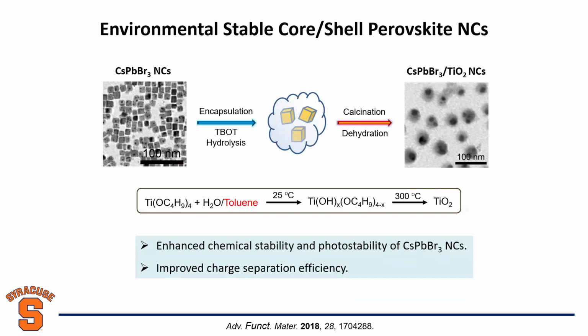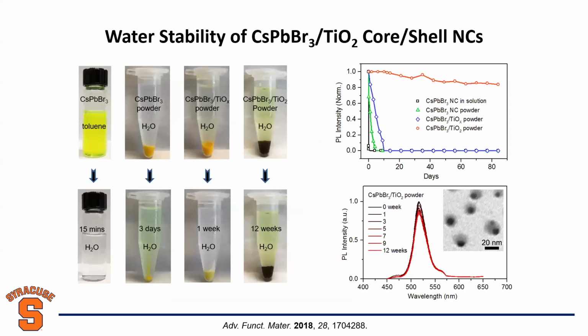And we found whenever we significantly increase the stability, we can also improve charge separation efficiency. Here I just give you one example. We did several stability tests: air stability, light stability, chemical stability. Here I just show you water stability, because this is the biggest challenge for the field. You can see without shell coating, if you put it in water for a few minutes, it's gone, like sodium chloride, a table salt, right? If it's dry powder, it can last a few days longer. In 3 days, almost gone.